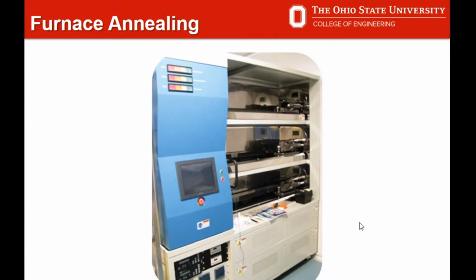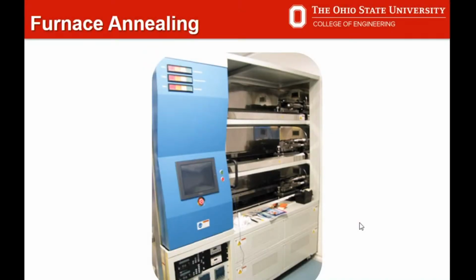So for example, some material has a sublimation temperature close to 1800 degrees centigrade. So obviously you need to be very careful about this temperature, because if a material has a sublimation temperature close to 1800 degrees centigrade, definitely you are not going for a very high temperature close to 1700 or say 1750. So definitely you'll choose around 1400 or 1500. Again, you have to be very careful about the type of environment you are looking for, like the gaseous environment, what you are actually looking to remove the defects from your material.